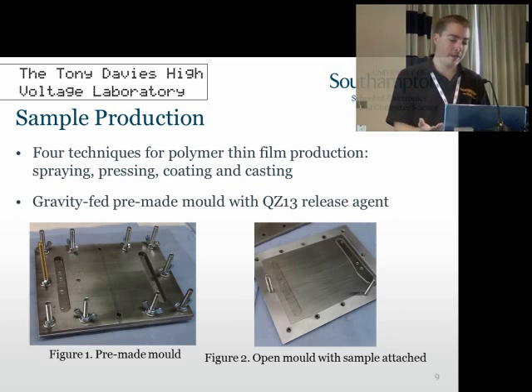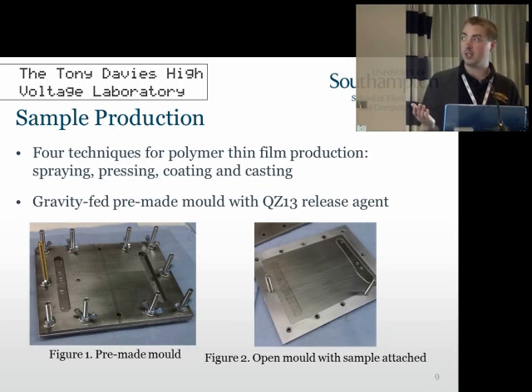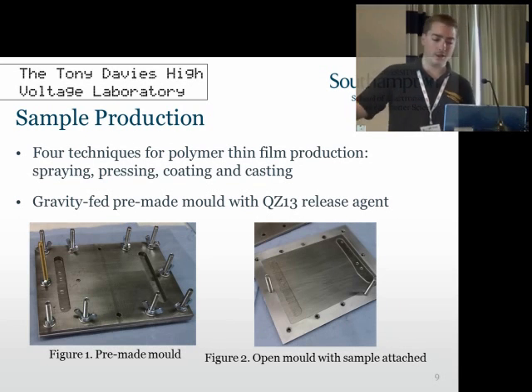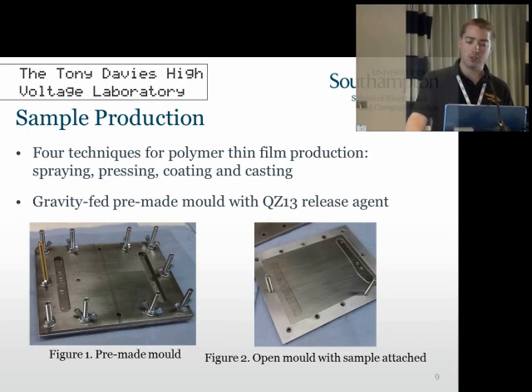Obviously, I basically confirmed that using moulds and casting these samples is the easiest method. So you can see in the 2 figures, this is the mould that we produced and used. We actually found that the resin we used was quite difficult to get out of the mould without damaging the mould or the sample. So we've been using a QZ13 release agent, which works well for the system.